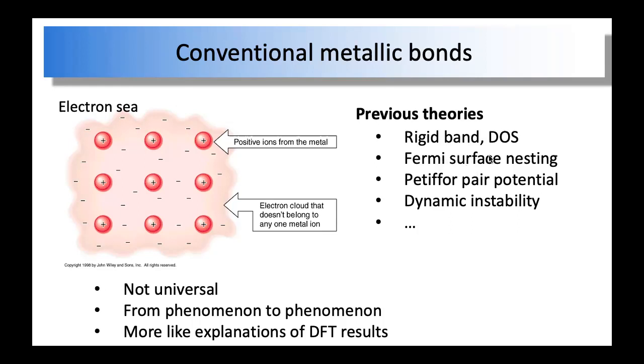And there's another theory, this very delicate Fermi surface nesting, right? That's particularly used to explain why, when we compress the metal, the structures change, and eventually they abandon the simple metal structures. And there are several others, for example, this very famous Pettifor pair potential. So these theories have several problems. The first is that no single theory can explain all the phenomena, right? And also very often the theory is basically just a description of the DFT results. It's not truly a mechanism hidden behind all this that you can understand with our mind, that is the driving force that drives the structure patterns and the structure changes.